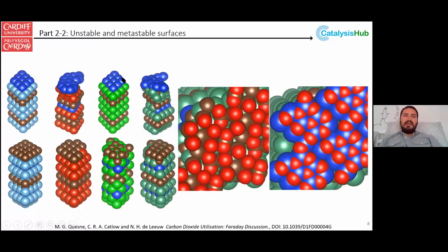So we found that the silicon and the carbon termination are really metastable states. This goes back quite well to what we saw with the monocarbides, that when you have the carbon layer, this is metastable. We found a very similar thing with the silicon carbides. So for the rest of the talk, I'm going to focus on the lowest energy slabs, which had silicon on the bottom and a metal termination on top, which is also what they see experimentally.